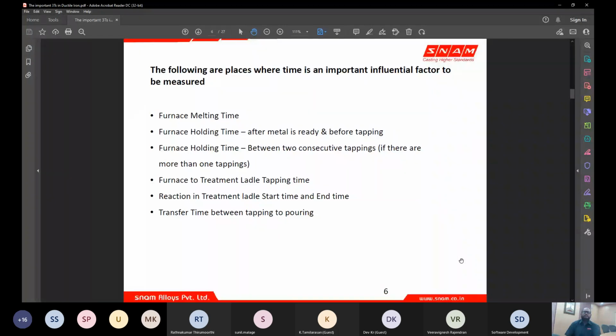So when you play with the charge mix, the furnace melting time increases. This has, to some extent, an impact on the nucleation potential, because the melting time involves a diffusion process where carbon is picked up from the carburizer we add during melting. When the melting time increases, that means we tend to add more steel, so more carbon has to diffuse into the liquid metal, because steel has almost nil carbon. If we are producing ductile iron, we need to make it up to not less than 3.2, 3.3 carbon, so we need to keep adding more carburizer. The time taken for diffusion will be more, so the diffusion process is a bit tricky, though not so significant, but it is also to be measured.